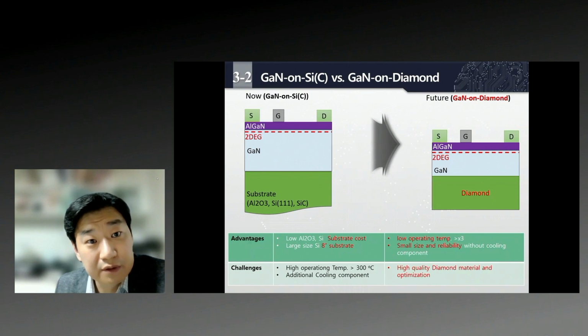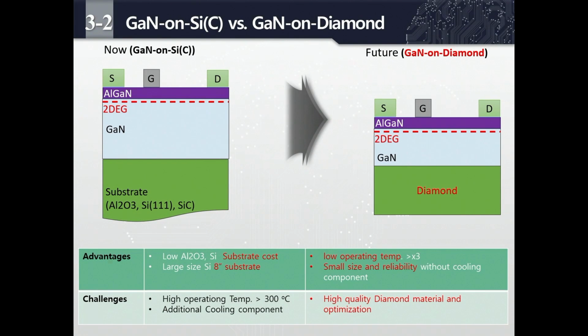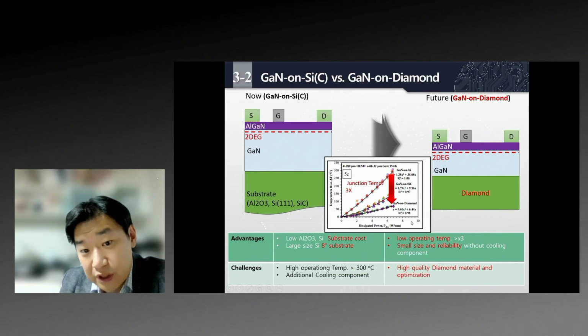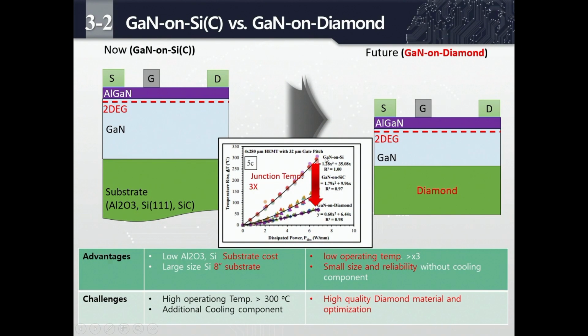So I will compare GaN on silicon or GaN on silicon carbide versus GaN on diamond. There are some trade-offs. The advantage of GaN on silicon is the cost of the substrate, and also we can utilize 8-inch or 12-inch substrates. But the problem is high junction temperature and the need for additional cooling components. GaN on diamond has lower operating temperatures, allowing small size and better reliability. But the problem is the cost of the diamond, and handling GaN on diamond is very tricky. With GaN on diamond, the junction temperature is the best, GaN on silicon is the worst, and GaN on silicon carbide is in the middle.